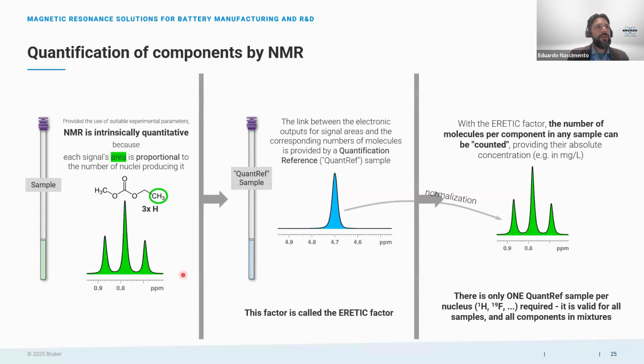So one of the main advantages of NMR is that the quantification here is done through external samples. This is because NMR is considered to be an intrinsically quantitative method. So when you see a signal in the NMR spectrum, that signal is proportional to the number of nuclei that you are analyzing. So using a reference sample, you can calculate that number as a reference. And then, for example, you can use water to calibrate your system, and then you can infer the quantification of the other components. So different from chromatography, for example, where you need to have the same compound to build a calibration curve and so on. With NMR, you don't have that. So it's very easy, especially when you are talking about unknowns, where you are quantifying things that are not so easy to buy a reference sample for.